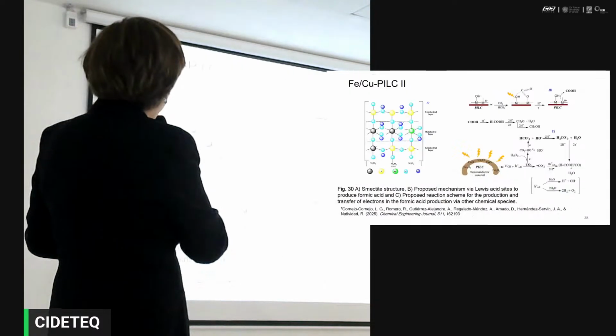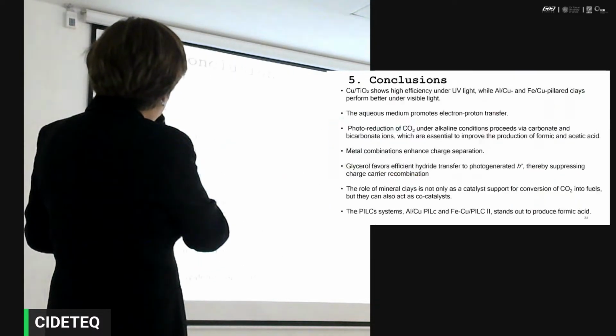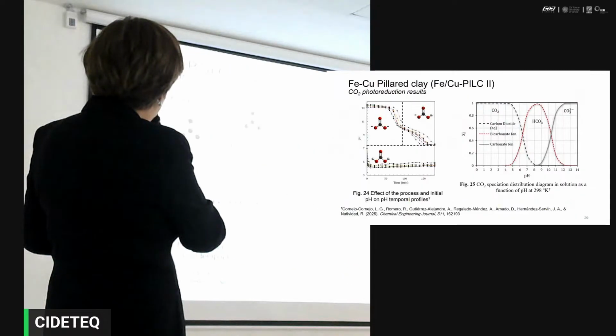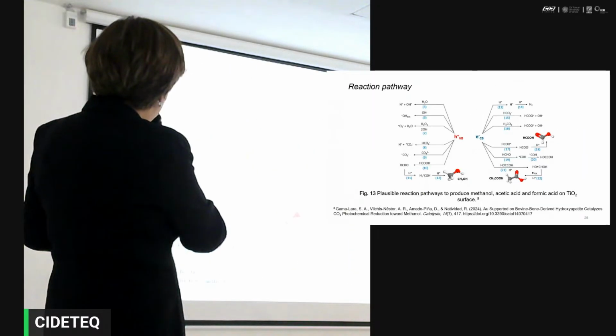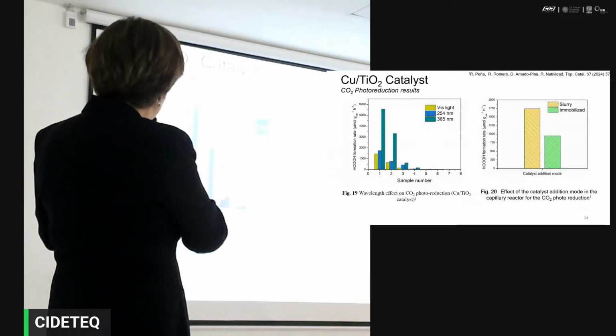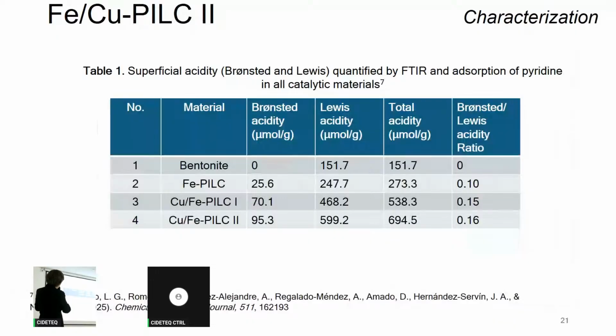No, the other way around. Okay, here I have a table where you can observe the acidity of the materials. Here, you can observe the bentonite has this Lewis acidity and 0 Bronsted acidity. So if you change the source of bentonite, that means that it's going to have a different proportion or a different ratio of aluminum and silicium, and that for sure is going to affect these two values. So we believe that would be affected, and then that affects the formic acid production.